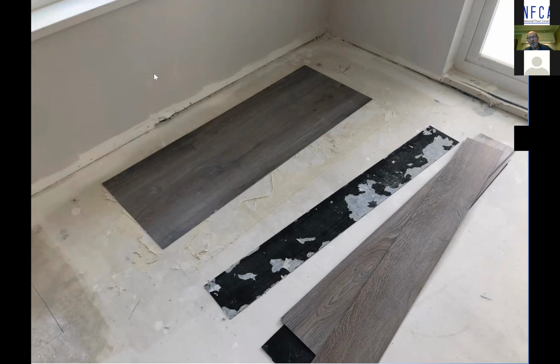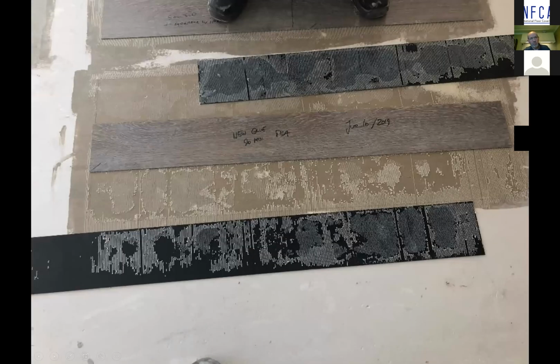In some cases, we've done tests and the adhesive works fine. No primer necessary. In other cases, a water-based material can also work. And then in some cases, we have to go to another level. So what's that next level? So what we had to do on this particular site, and there was probably 60,000 feet of LVP going into this particular job, so it was pretty significant. It was 5 stories. And we kind of figured our PSI strength was somewhere around the neighborhood of 2,000.